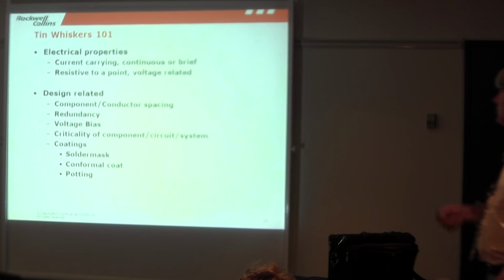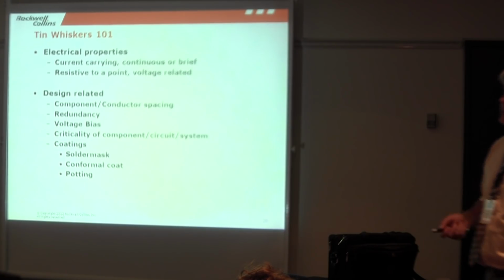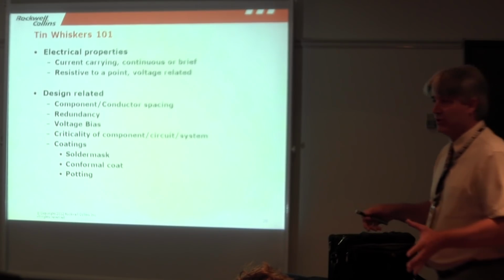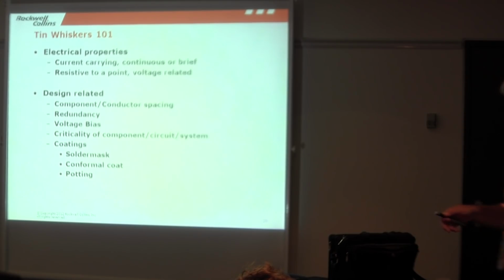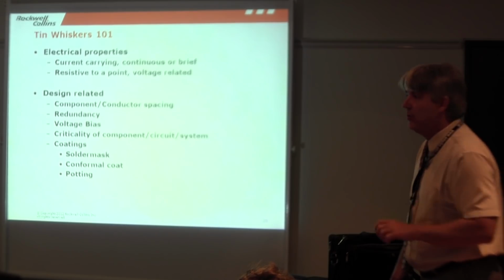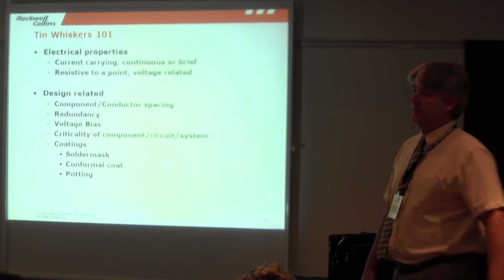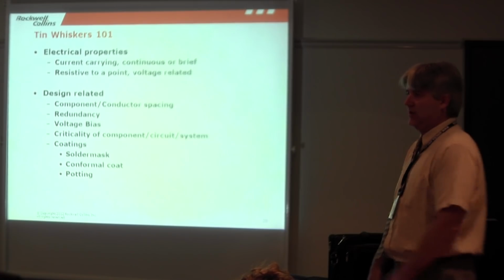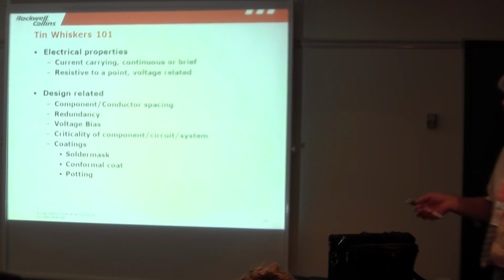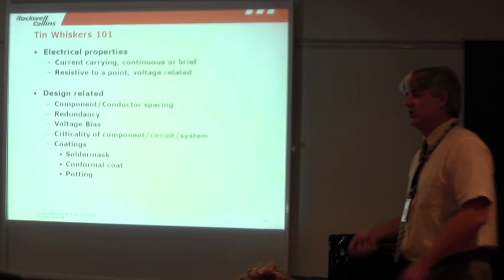help me. You also see, and I think I touch on it in here, there's a new class of conformal coatings coming out. Some of them are vapor deposit, a lot like Parylene, but different formulations. There's also things like Rockwell Collins working on a liquid glass, where they're angstroms thick. And those have great promise because the RF doesn't care about a coating that's an angstrom thick. You put it 2 or 3 mils thick, okay, now RF and microwave can't stand it. The designs just don't work. So we've got to find those in-between materials that'll work in those cases. And I should cover part of that.